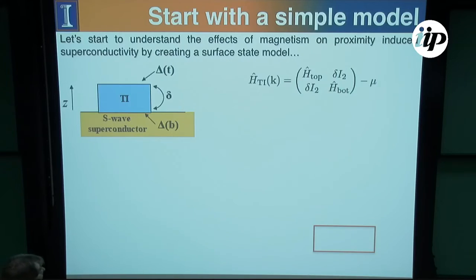So what we did is we started with a very simple model where we just form a topological insulator Hamiltonian. This is based on the work of Marcel Franz. His name is not on this slide, but it certainly deserves to be because this is where we started. He came up with a very nice model that's very simplistic. It takes away the bulk, and for doing an analytic calculation, getting rid of the bulk is really a handy thing to do. So we have the top and bottom surface states connected by some sort of simple term.